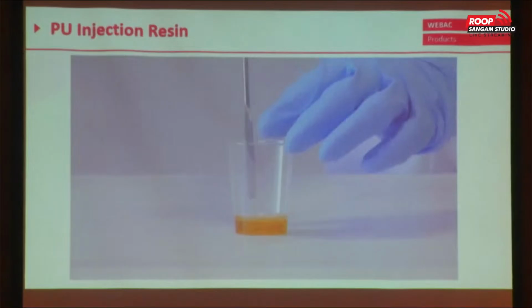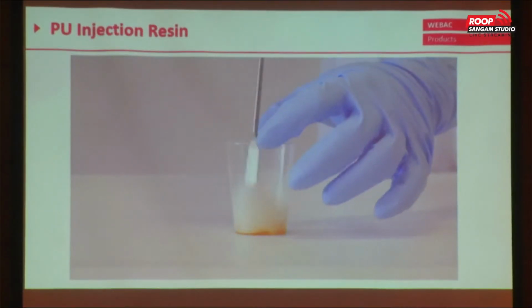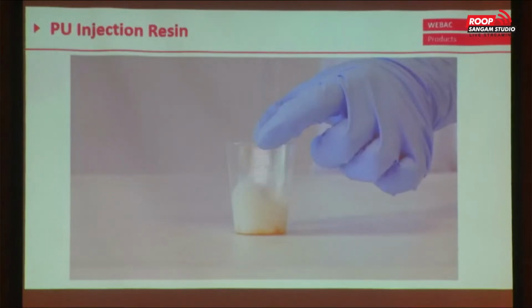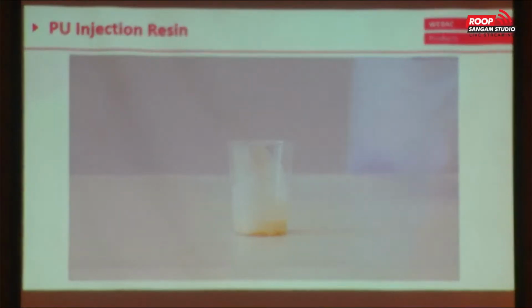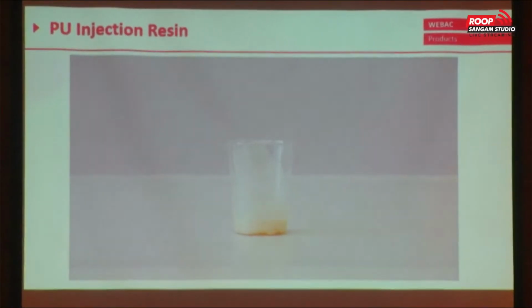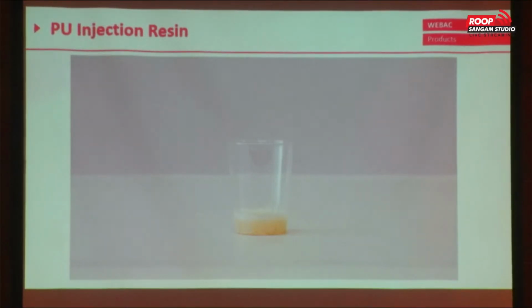But here we see a reaction of such a form. Have a look at the viscosity. We speak about 80, 90 millipascal-seconds. If you have it in a canister, it's really liquid. That gives us the possibility to penetrate fine cracks, fine fissures, and deep structures. This is now not real time, it's a time loop, because we want to push the material or inject the material as deep as possible. If it would react earlier as a foam, you are not able to get into the depths, which is important in this case.